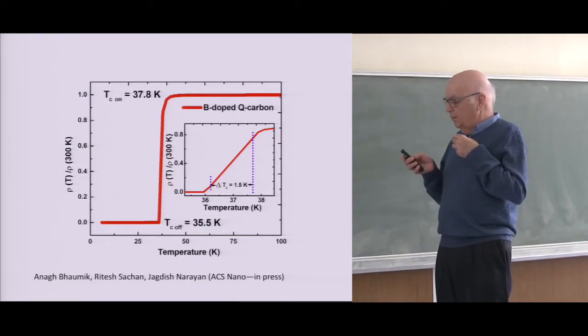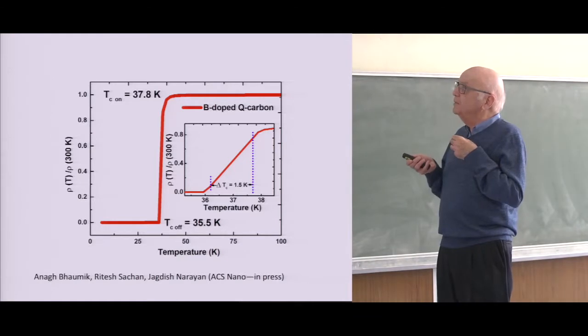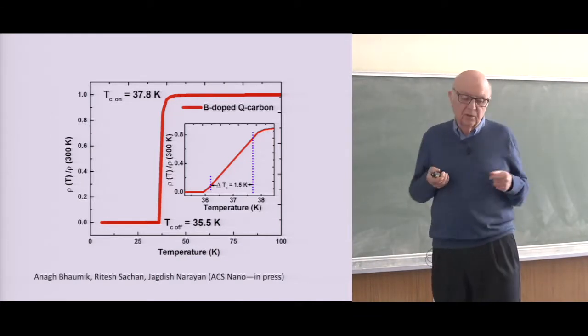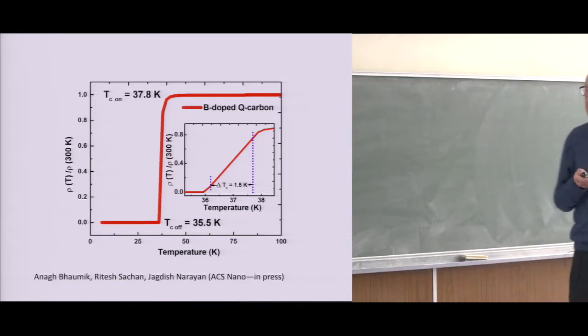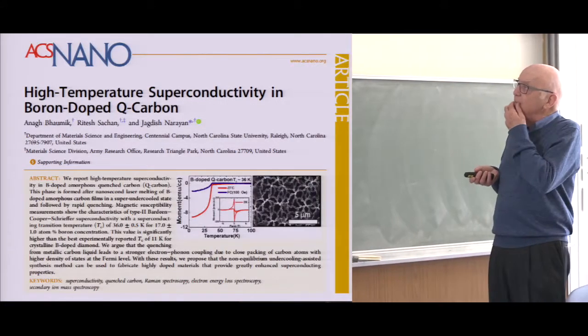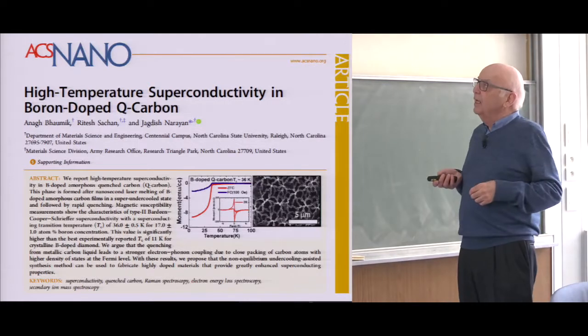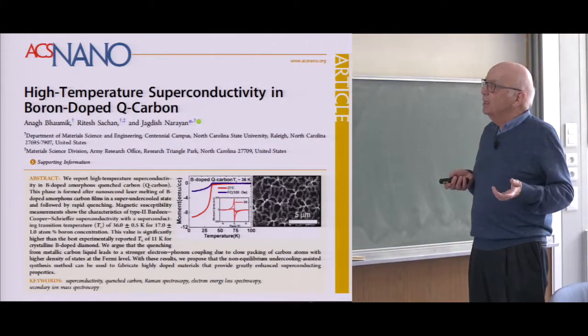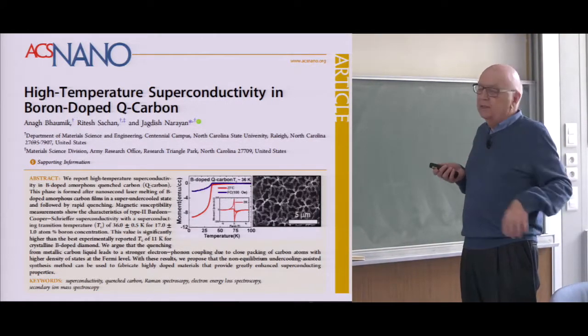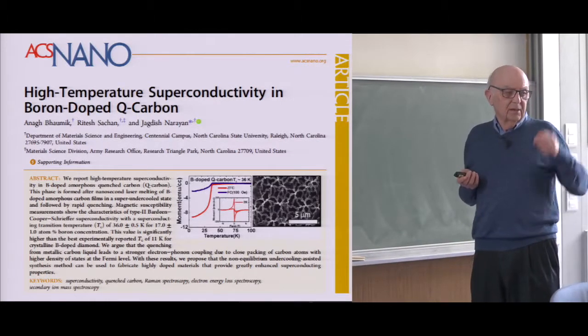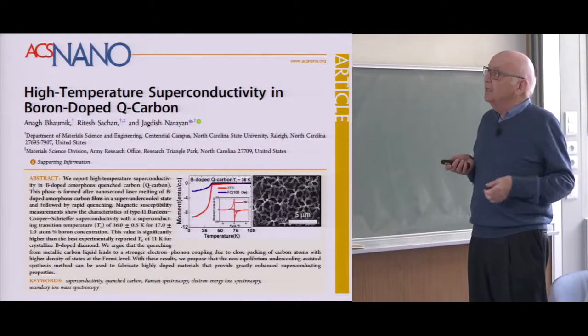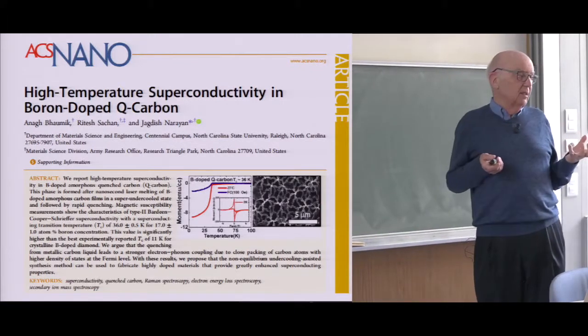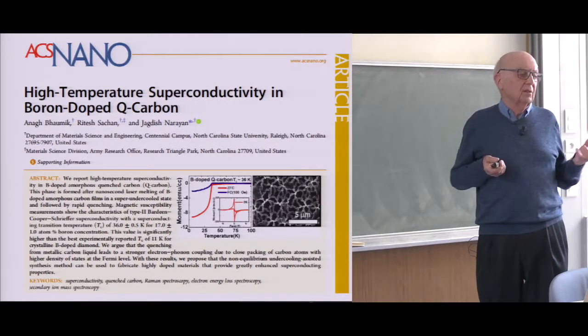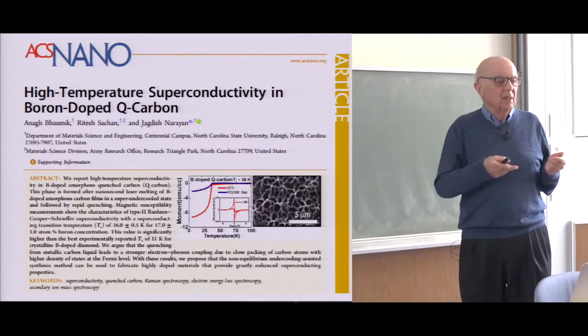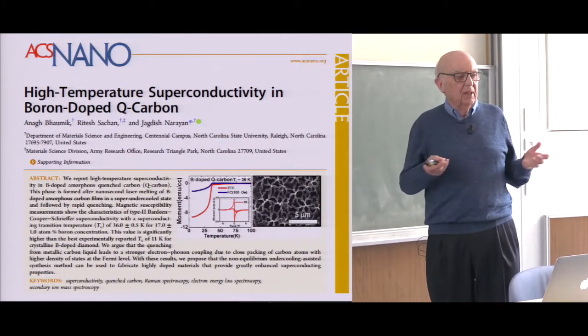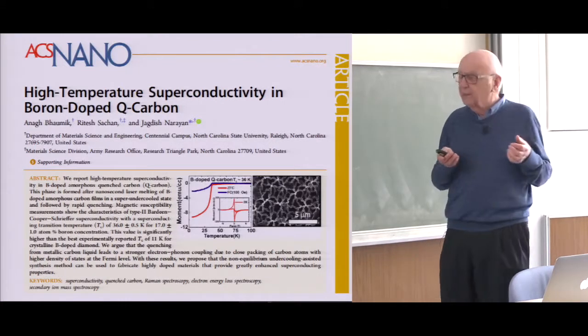And he did magnetic exclusion and so forth to show that it's superconducting. So the paper is now published, and this is all I know about the details. You know, with superconductors, you have to be careful. Unless you do a heat capacity, you don't know the whole thing is superconducting. If you do resistivity, it could be something else. But if you're at 36 degrees and there's only carbon and boron in there, it's still interesting.